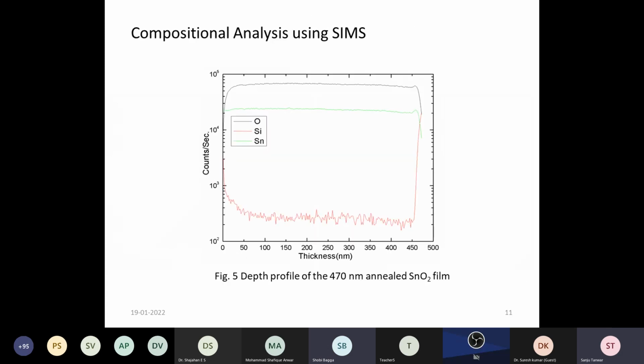And the second thing we look at: because it's a mixture kind of film, with tin and oxygen, there are two components. Its composition can be measured using XPS, but that only gives information about the surface composition. If you want to see across the depth how these things are deposited, what is the ratio of oxygen and tin across the thickness, that has been measured using SIMS. SIMS is known as secondary ion mass spectroscopy. What it does is, we take the film and bombard it with a high-energy ion beam, and the ions coming out are detected using the mass spectroscopy system.